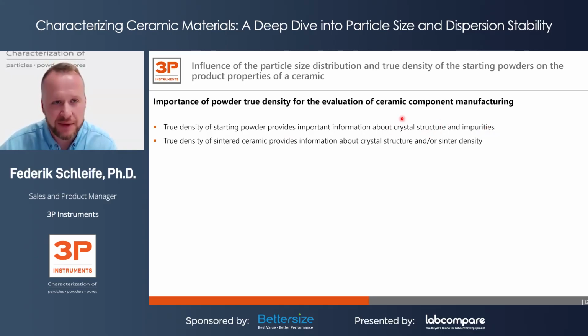So depending on what your raw material is, for instance alumina or zirconia, of course they have different true densities. And you can imagine, in case there are some impurities in your starting material, you might measure a density different from the density of pure alumina or pure zirconia. So therefore, true density measurement can already be a quality indicator regarding the impurities of the raw material. But furthermore, those materials also come with different crystal structures, and these could also be identified by measuring the true density.